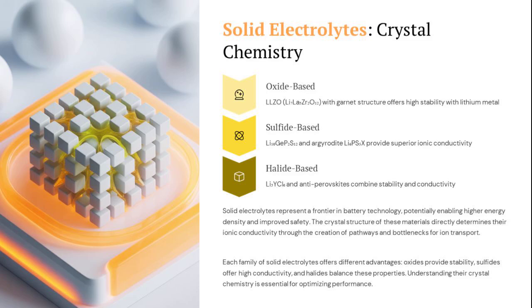What makes garnets attractive is their combination of reasonable ionic conductivity, 10^-4 S/cm at room temperature, wide electrochemical stability window, and compatibility with lithium metal. However, challenges include high grain boundary resistance and poor wettability with electrode materials.